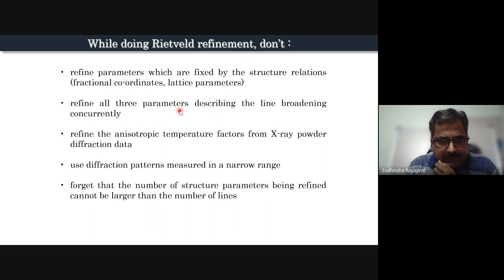When you are trying to refine the half-width parameters, what you have to understand is that among the U, V, W, X, and Y parameters, U, X, and Y have influence from the sample. Otherwise, U, V, W is basically an instrumental parameter. So you can refine U, X, and Y. You can adjust V and W depending upon the instrument which you have used at that time. But mainly, if you are working on a systematics of samples, then you have to look into U, X, and Y parameters only. And by the function, V is always negative, so you should keep that in mind when you refine. You should not refine blindly. You have to keep an eye on what is going on.